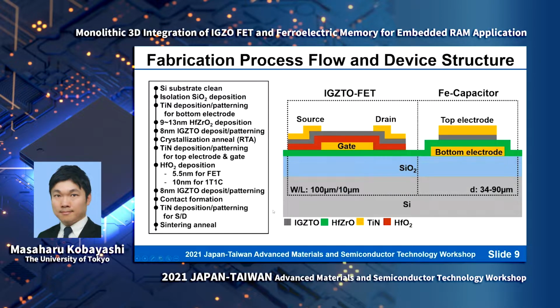So here is the process flow of the 3D monolithic integration, and also a cross-sectional schematic of the demonstrated device structure. Basically, we started from the clean substrate and passivated the surface with SiO2. Then we fabricated a ferroelectric capacitor and also a tin-doped IGZO transistor on the same layer. The ferroelectric capacitor consists of a bottom titanium nitride layer, a ferroelectric hafnium oxide layer, a tin-doped IGZO capping, and a titanium nitride pad. So this is a ferroelectric capacitor. And we have a back-gate type tin-doped IGZO channel FET with a titanium nitride bottom gate and titanium nitride source and drain.